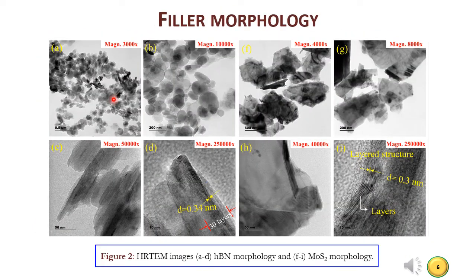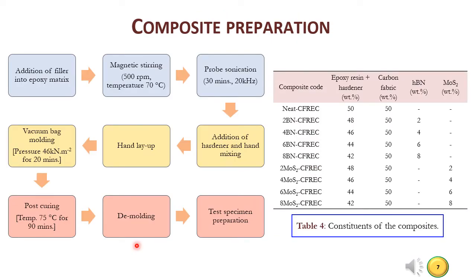Morphology of hexagonal boron nitride and molybdenum disulfide at various magnification can be seen, obtained through high resolution transmission electron microscope. Most hBN particles are in discs and few are in flake. MoS2 resemble thin sheets. The flowchart indicates steps involved in composite preparation. Table 4 indicates constituents weight percentage.